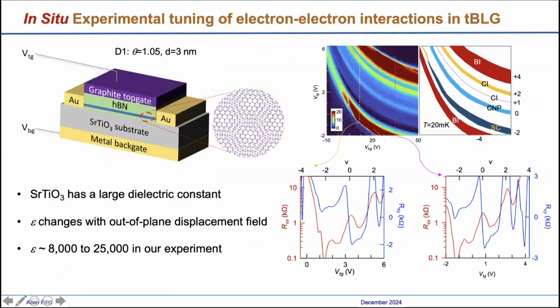So what we do here is put twisted bilayer graphene on a strontium titanate substrate. They're separated by a thin layer of hBN, which is 3 nanometers. This particular device is at a measured angle of 1.05 degrees. Turns out strontium titanate has a large dielectric constant. I should also say we have a top gate, which is graphite, separated from the twisted bilayer graphene by a thick hBN.